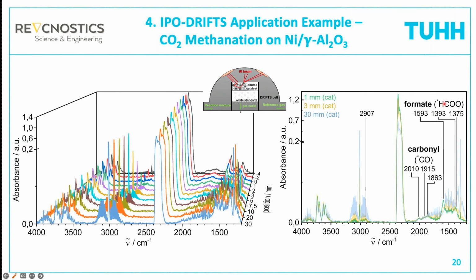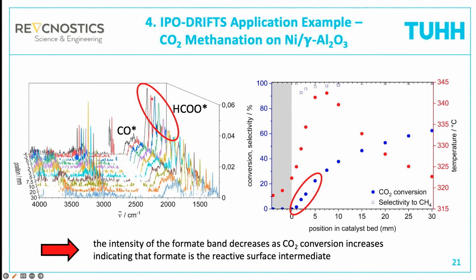And now we can calculate this double difference and back out the signals of the surface adsorbates, and this is shown now in this plot here. And what you see is that we have adsorbed CO all along the reactor, but it doesn't change. So in catalysis, this is called the spectator species. It is there. We see it spectroscopically, but it obviously does not partake in the reaction. So it's just a spectator.